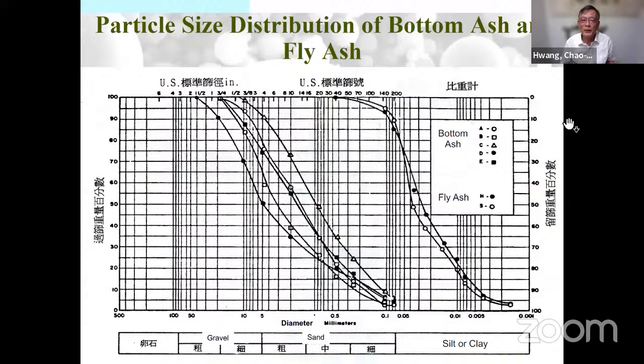Looking at the particle size, fly ash is actually a small particle, so it has very good gradation. By looking at this one, it can be used to replace cement or replace some sand also. And look at the bottom ash, the particle size is large, and this one can replace part of sand. Next, please.